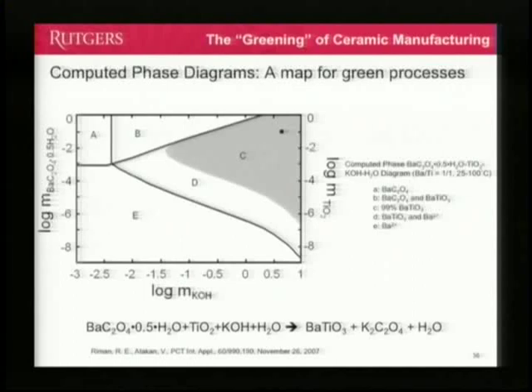So the way we start is calculating a phase diagram using thermodynamic principles. And so this shaded area here shows you where you need to run your reaction conditions in order to run this reaction, where we take an oxalate and we react it to form barium titanate. And this is actually an equivalent reaction. This is actually a single compound, but this is the only way we could model it. So this model told us if we add lots of KOH to the system, not only will we get barium titanate, but we won't release any CO2.